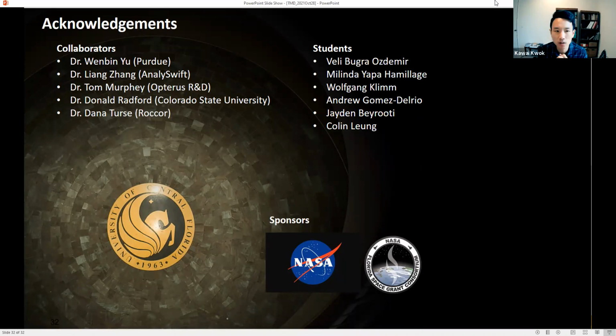Yeah. So I didn't show it here, but we actually looked at two particular kinds of variability. One of them is thickness. That was described in the paper, but I didn't show it here. The thickness variation is quite a main factor. I think it's very hard to control thin film manufacturing to a very uniform thickness, and from process to process, from batch to batch, the thickness varies, and that changes the stiffness quite a lot, as you know from beam theory. So we did do a sensitivity study on what range we can expect from this sort of thickness uncertainty.